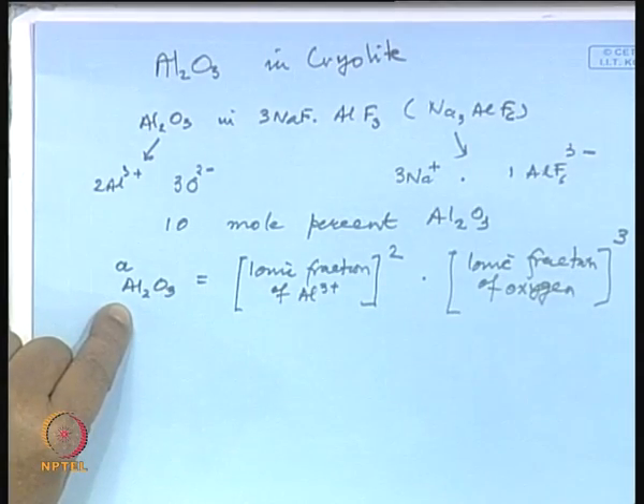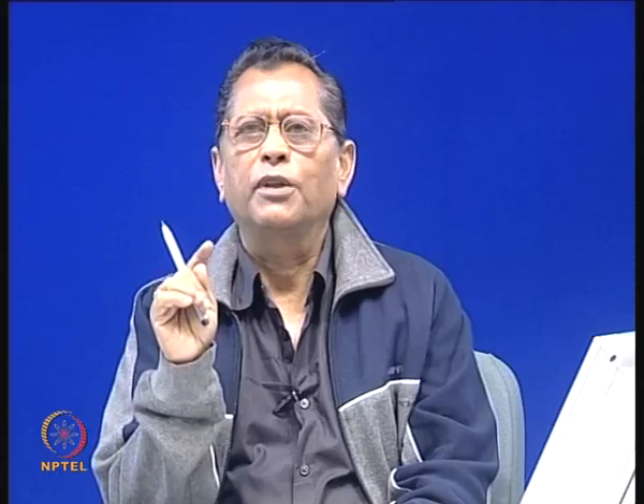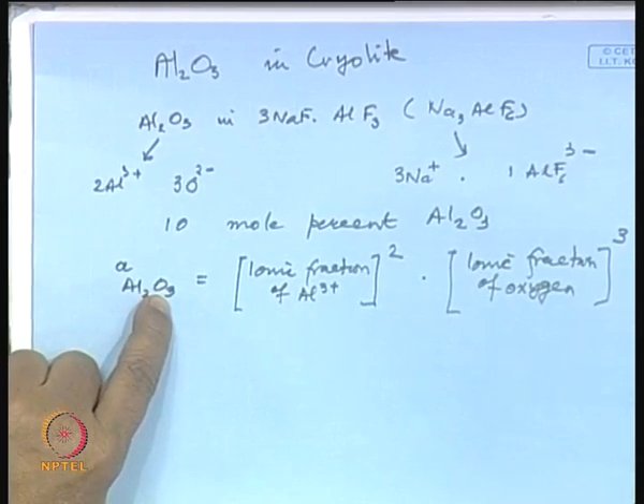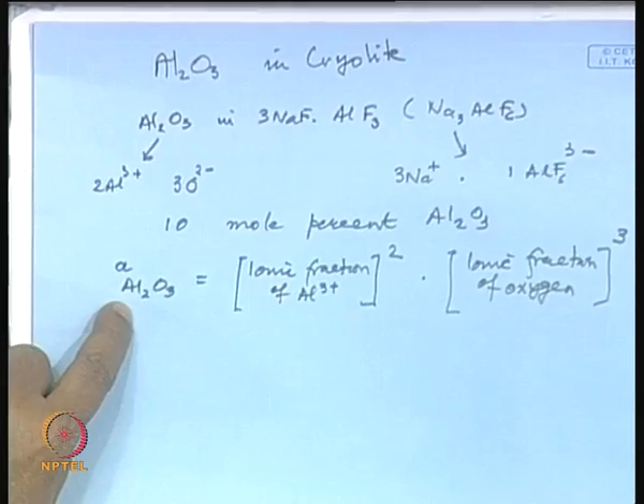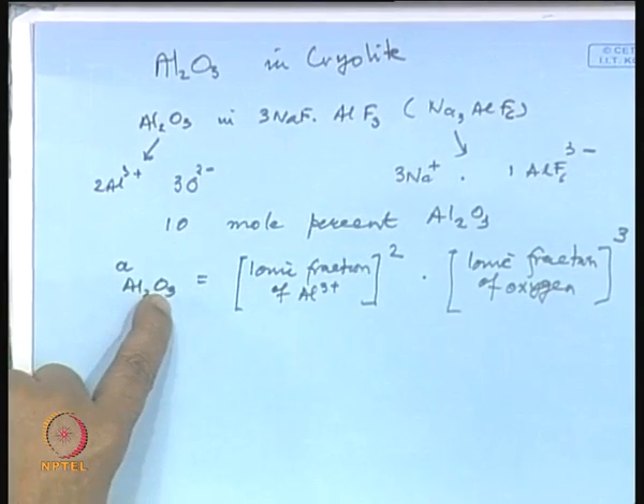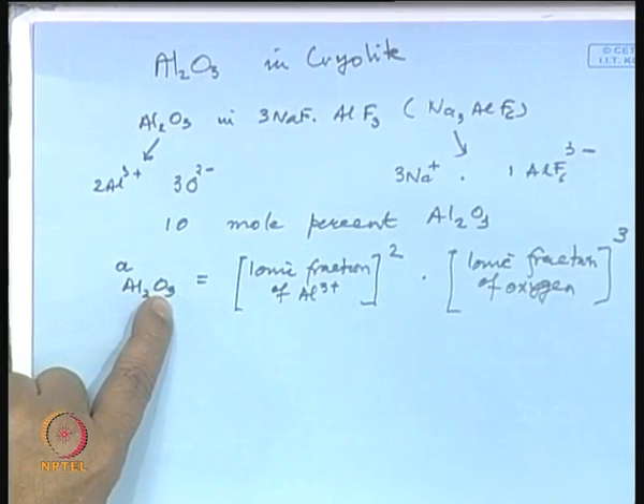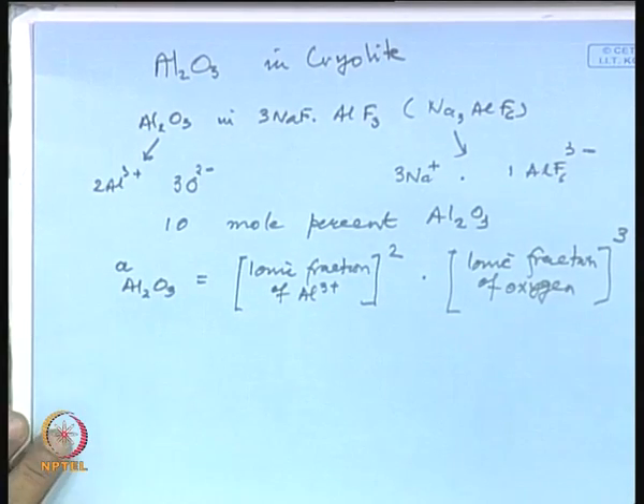Now, the probability of finding two aluminum ions will have to be calculated with reference to only the cation sublattice. Probability of finding oxygen anions, 3 of them in nearby areas, will be in reference to only the anion sublattice. And because we are calculating probability, we are talking about 2 aluminum. So, it will be ionic fraction of aluminum to the power square, and this will be ionic fraction of oxygen to the power cube.